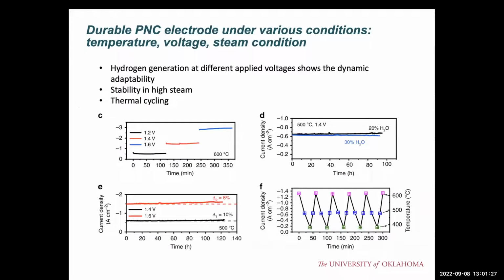Here it also shows some examination of the chemical and electrochemical robustness, by changing the temperature, voltage, and also steam conditions, because these are the prime parameters in the steam electrolysis process. We changed the voltage from 1.2 to 1.4 to 1.6. We changed the steam from 20% to 30%. We operated for different time periods. We even changed the temperature from 400 to 600 degrees C to simulate thermal shock or thermal cycling, to see how this kind of SOC ceramic structure can tolerate the thermal shock.